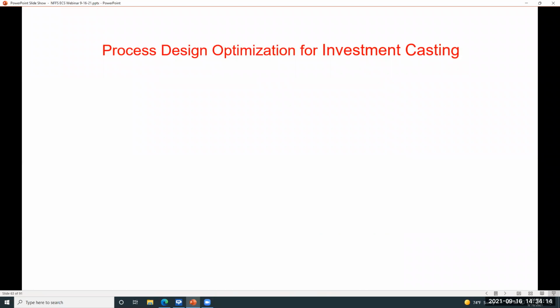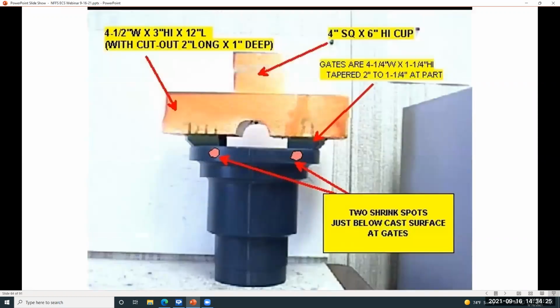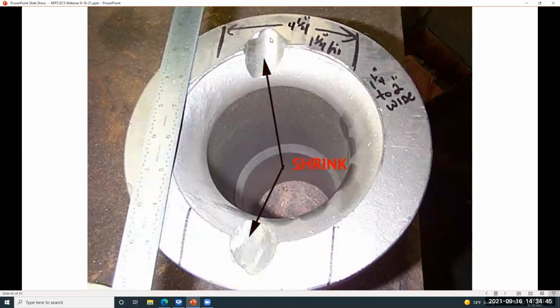Let's take another example, a very quick look at adding the idea of optimization to the process. This will be done for an investment casting. This shows the wax pattern, and you can see initially that one of the problems that they were having at the foundry was that they were getting internal shrinkage in the casting below the in-gate. So they were actually gouging out so that you can see the shrink area below the in-gates here.